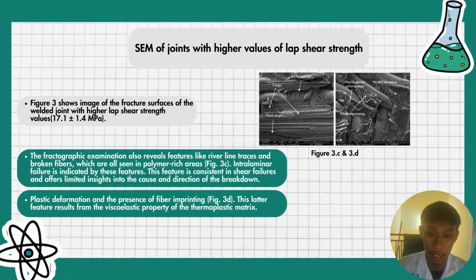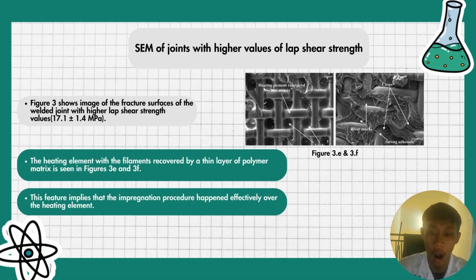Plastic deformation and the presence of fiber imprinting in figure 3d is shown. These latter features result from the viscoelastic properties of the thermoplastic matrix. The heating element with the filament covered by a thin layer of polymer matrix is seen in figures 3e and 3f. This feature implies that the impregnation procedure happened effectively over the heating element.